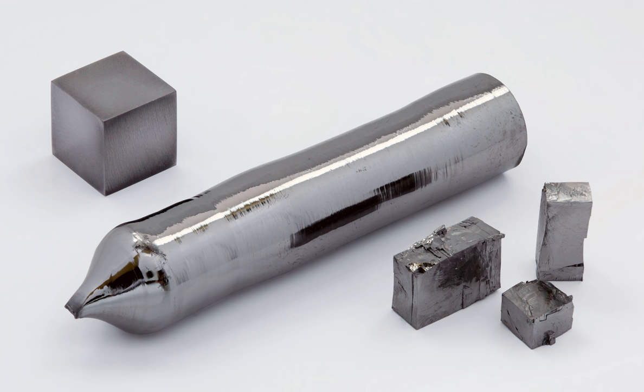K2TaF7 can be converted to metallic tantalum by reduction with sodium, at approximately 800 degrees Celsius in molten salt. K2TaF7 + 5 Na → Ta + 5 NaF + 2 KF. In an older method, called the Marignac process, the mixture of H2TaF7 and H2NbOF5 was converted to a mixture of K2TaF7 and K2NbOF5, which was then separated by fractional crystallization, exploiting their different water solubilities.